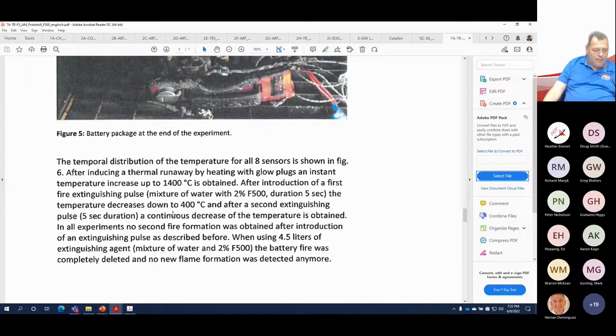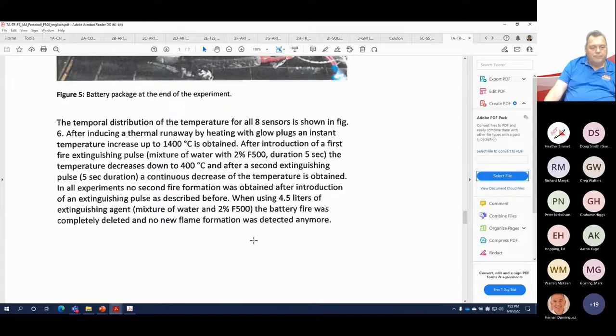Then after the second extinguishment, a continuous decrease of temperature is obtained. So we got 10 seconds of agent, all experiments, no second fire formation was introduced, the extinguishment as described before. So they used 4.5 liters of the mixture to extinguish this fire and to prevent burn back resistance.